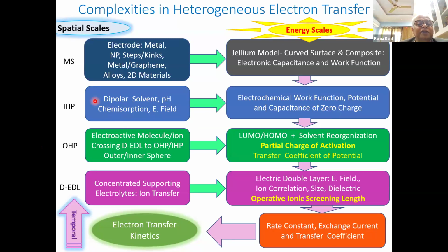And then another thing is the first layer of, say, solvent dipoles at the interface. This is very important to include because most of the people who are doing extensive computation avoid putting in this solvent, but the electrode will see through this solvent layer. So you have a dipole layer. If you have pH also, that will have some kind of H-ion or OH-ion adsorption at the surface, which will change the properties. You can have chemisorption, which will change things, and you have an electric field, which will interact with all this dipole, which is emerging out of the metal, which is strong but very short.